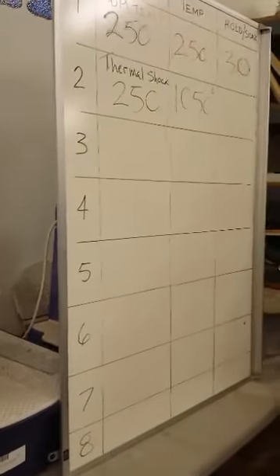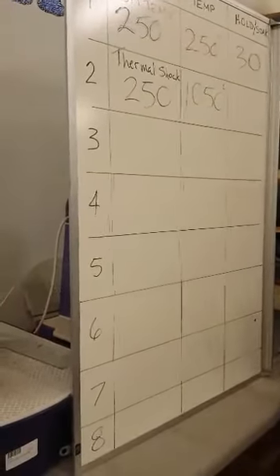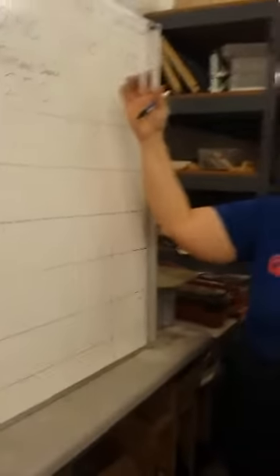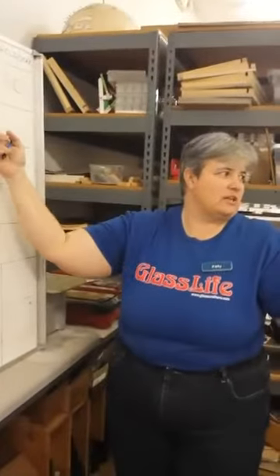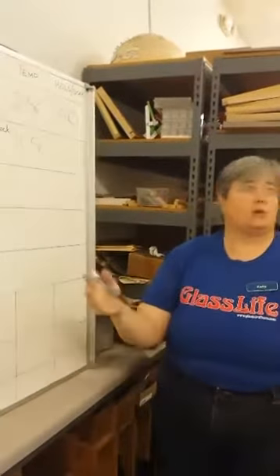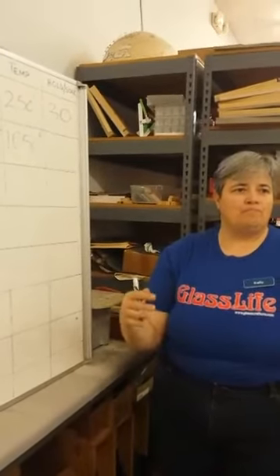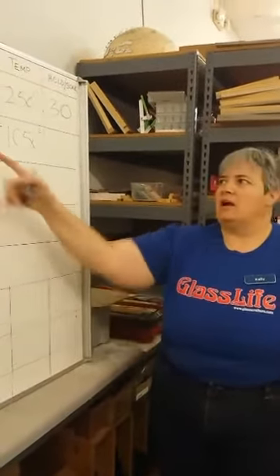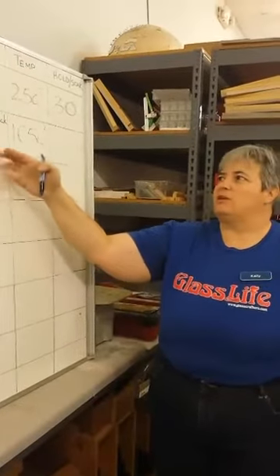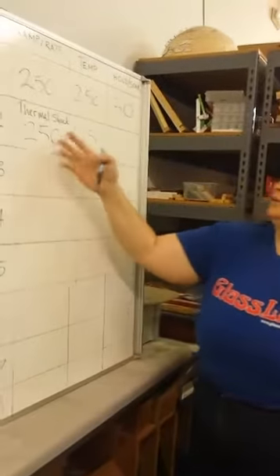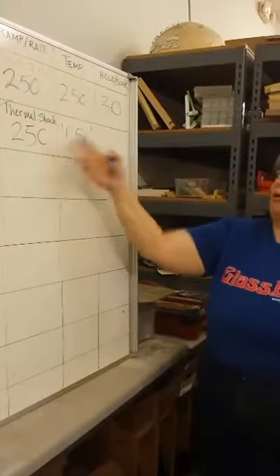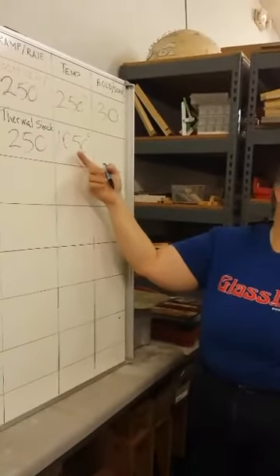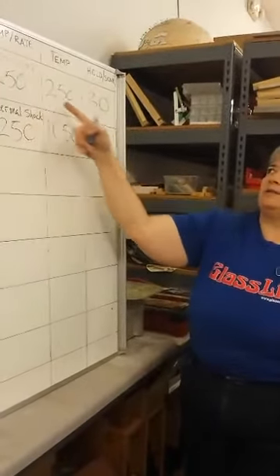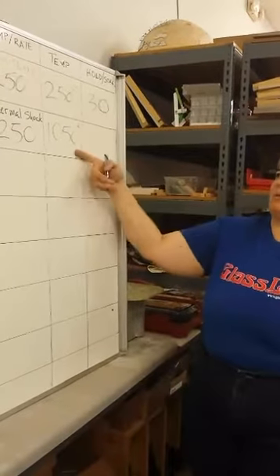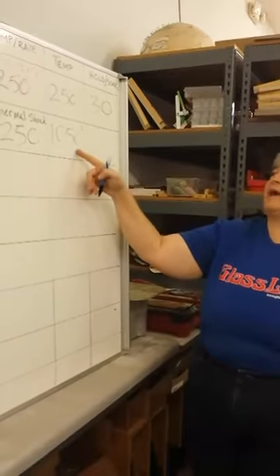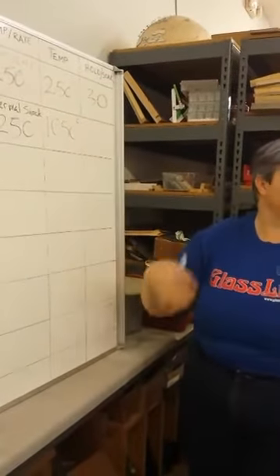Now, if I have a small project like earrings or a pendant or something, I can pretty much ramp that puppy up, and I can go faster than this to get to that. But if I have a large project, I'm doing a large plate, I'm doing a complicated project that has more than one layer in it, I want to stay at a slow temperature to get here. So at 250 degrees an hour, I'm looking at 4 more hours before I get to that. I'm going to go 3 more hours because I've already gone a quarter of the way to that temperature here. And now I've got to go the rest of the way, but I'm only doing 250 degrees an hour. So I've got another 3 hours before I even get to the point where the glass is going to move.